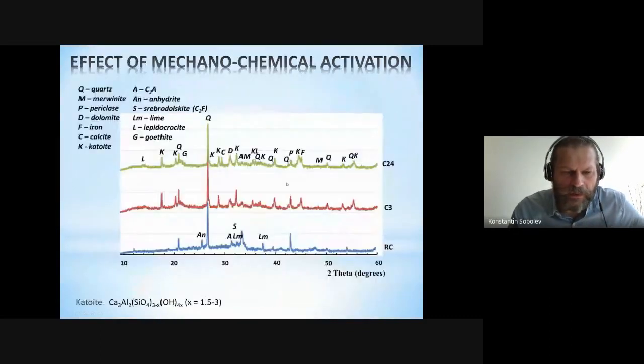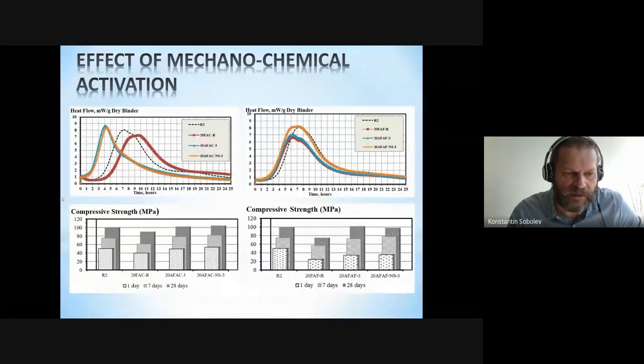And upon activation, what we realized is that we have formation of, even after 3 hours, activated cement. After 3 hours, we have the formation of calcium aluminosilicates such as katoite products after 3-hour hydration. So this can be easily detected, and those products were actually the main acting products of nanomaterials accelerating the hydration process of the system with activated class C fly ash.